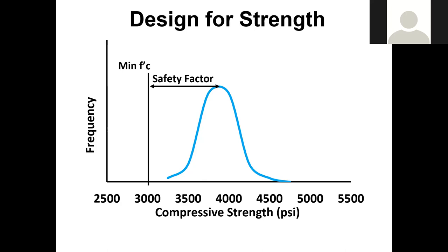Unfortunately, even if you make it designed at 10,000 PSI, eventually you'll have a little break. That's all the way out there statistically. So there's some statistics that we'll talk about next time about how to design a concrete mix, but you always design it well above 3,000. It may be 3,800, maybe 3,600, depending on how your distribution is. Sometimes it may even be 4,000 or 4,200 you may try to design at. But there's always a safety factor so that most of your concrete's gonna be well above that 3,000 or whatever